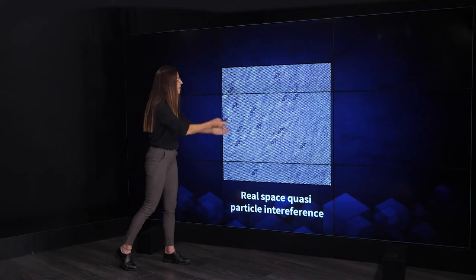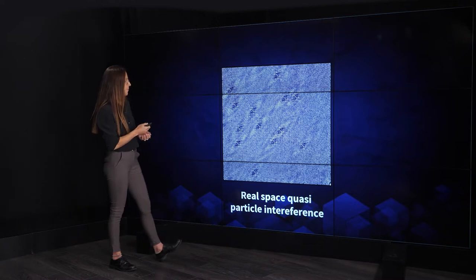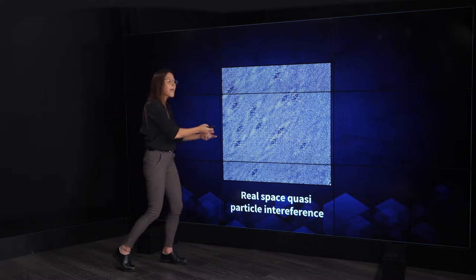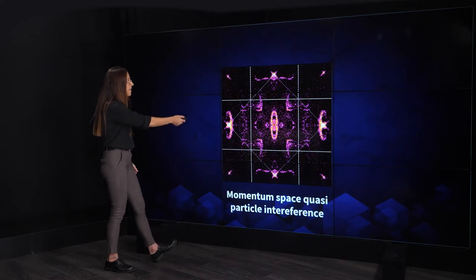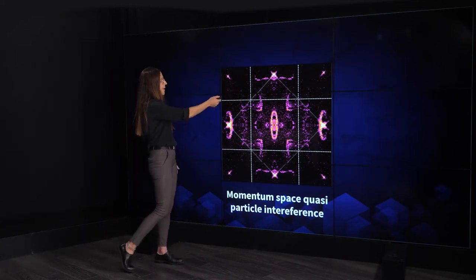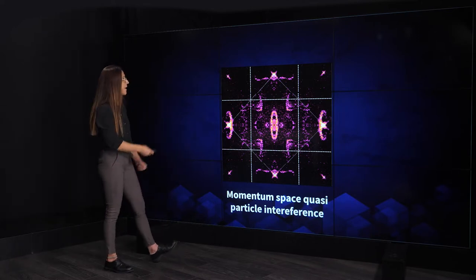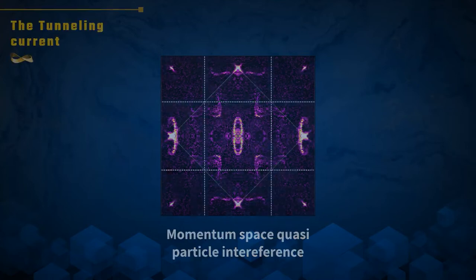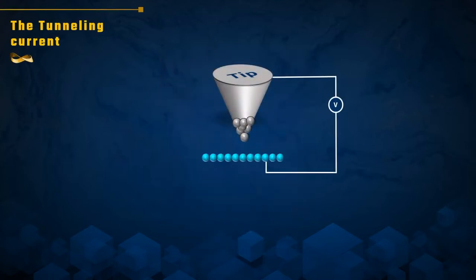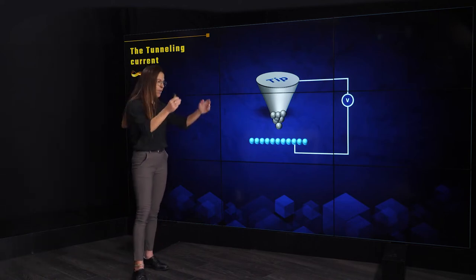This is another image taken on the same region with the same scale; however, what is shown here is the local density of states as a function of position. We see that in the clean region we see the signature of the crystal structure, but around the impurities we see elongated modulations of the density of states that are called real-space quasi-particle interference patterns, and we see that they are not commensurate with the crystal structure. If we take a Fourier transform of this image, we see beautiful quasi-particle interference patterns in momentum space, which are directly related to the surface band structure of the material.